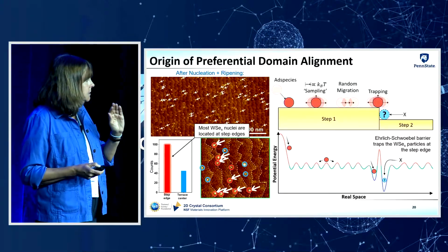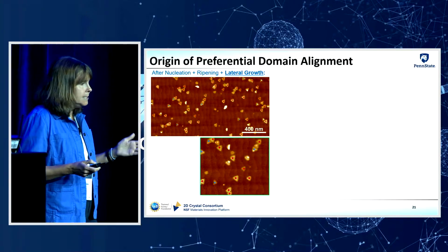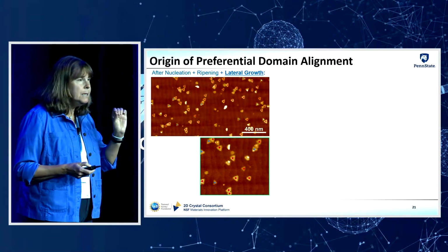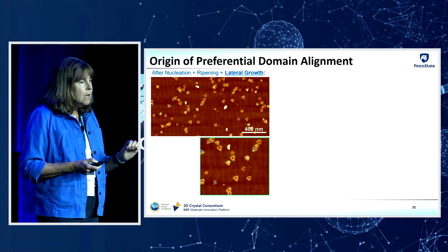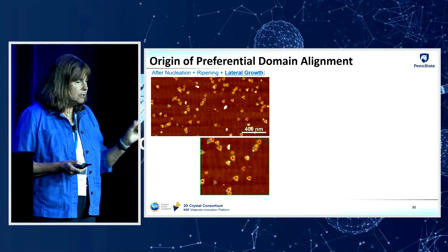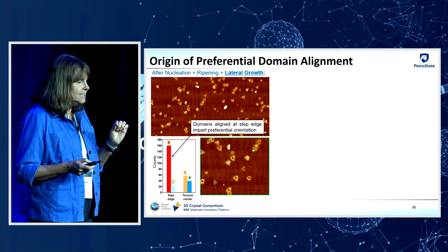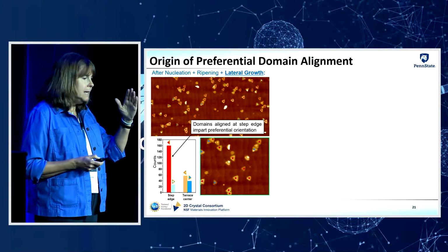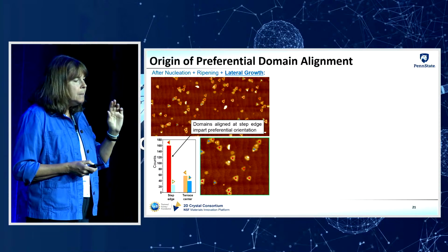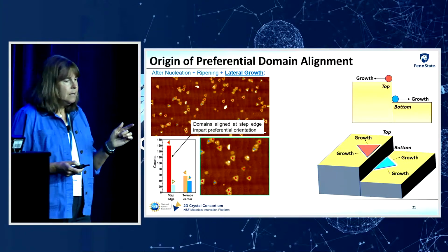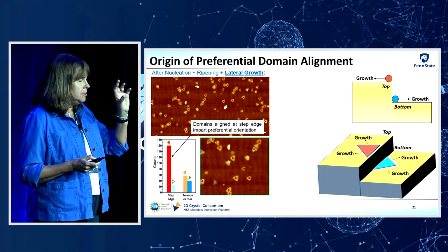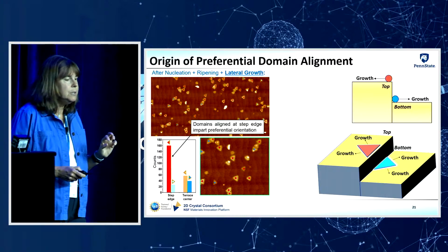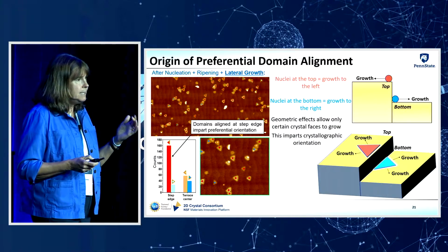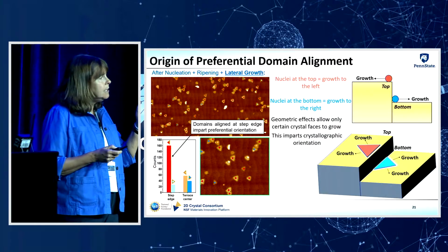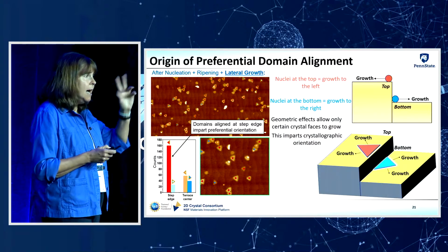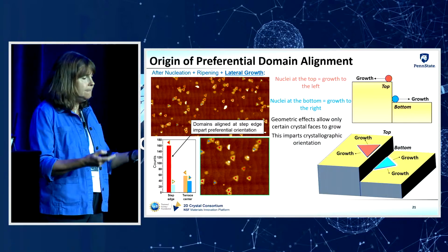So we wanted to take a closer look to see exactly where the nucleation was occurring, and we used our three-step process again, but now we extended the lateral growth time a little bit longer so that we got triangular shaped domains. That gave us a way to see exactly where the nucleation is occurring on our step sapphire surface. And again, I've color-coded the domains, and you can see that the majority of the domains are nucleating at the step edges, but in particular, they're nucleating at the top edge of the step, right? I've color-coded red for domains that are nucleating at the top of the step versus blue for those that nucleate at the bottom edge of the step. So the presence of steps on the sapphire surface gives rise to this preferred orientation. And if we can control it so that most of the domains are nucleating either at the top or at the bottom of the step, that gives us a way to reduce inversion domains in the film.